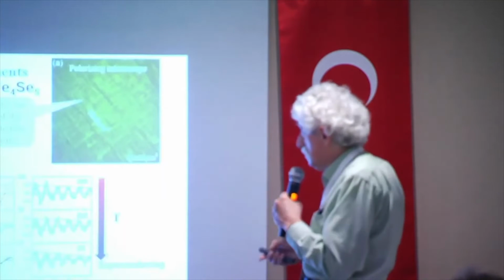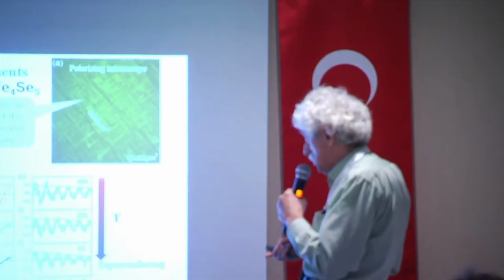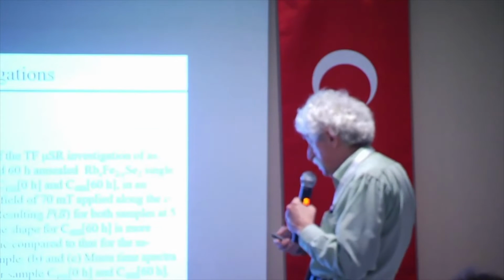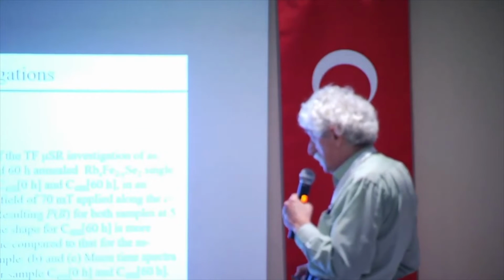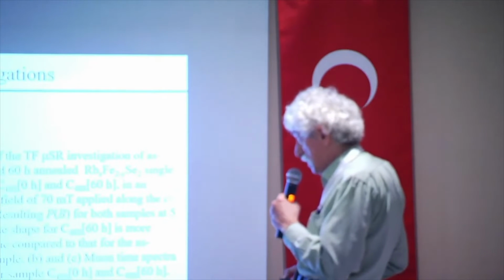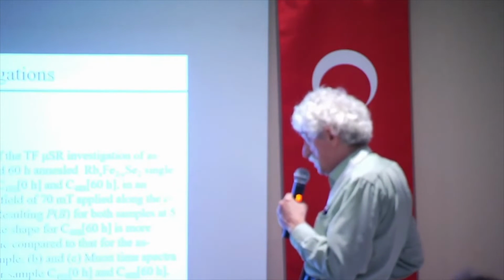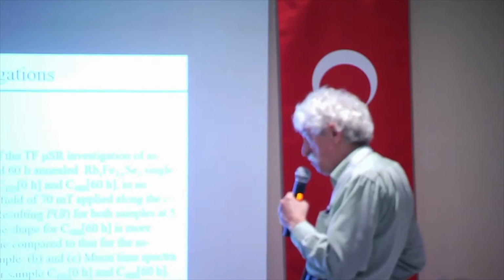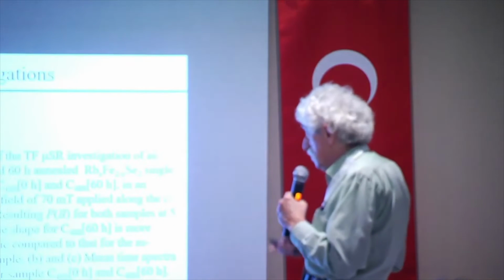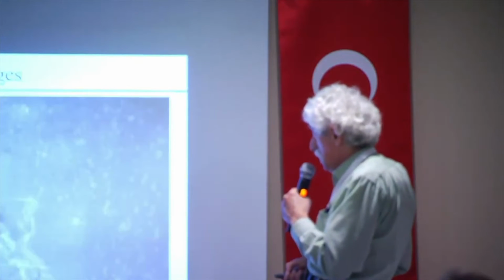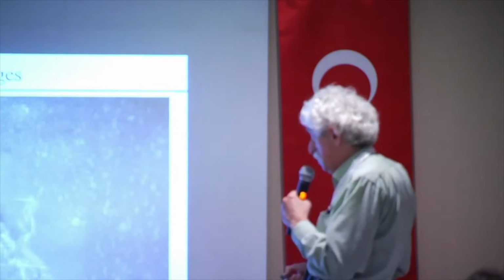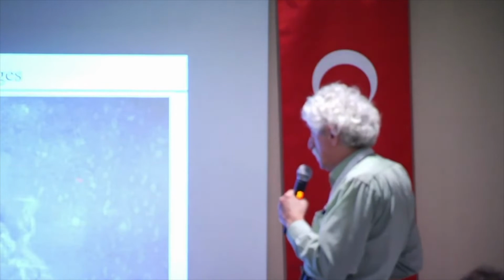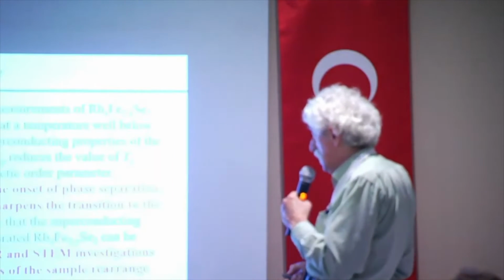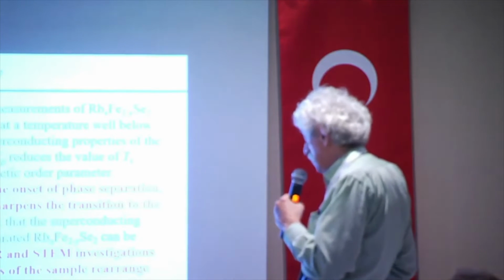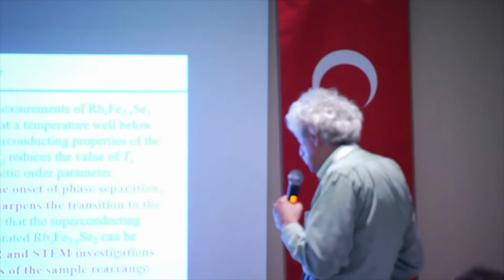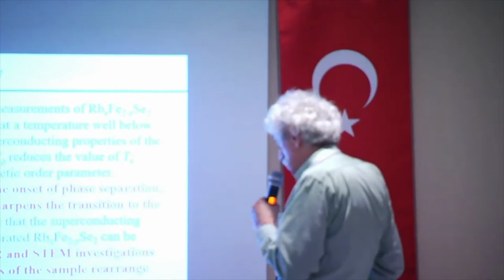So in order to know what this means, we performed mu-SR measurements, and the most important picture is probably this one: the sample which was not annealed shows very homogeneous magnetization inside the sample, but this magnetization became much more inhomogeneous after annealing. So this is again a mu-SR measurement, and these changes observed by mu-SR are correlated with changes in the scanning transmission electron microscopy image, and so this is a conclusion of our work that both mu-SR and scanning transmission electron microscopy investigation show that